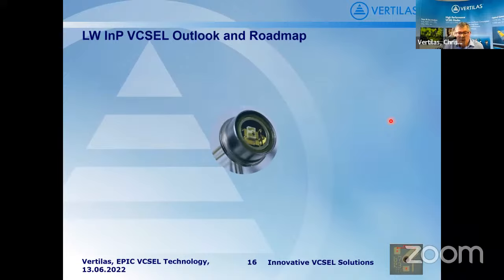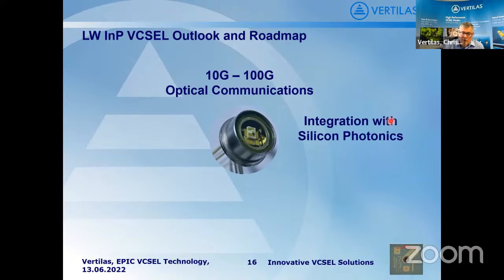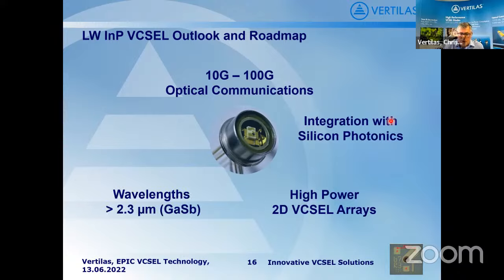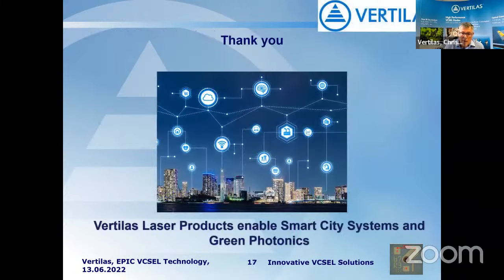Okay, so that brings me to my summary. This technology, indium phosphide VCSELs, allows you to address 10 to 100 gigabit optical communications. Of course, at module level, that's a multiple of that. Integration with silicon photonics. You can manufacture high-power 2D VCSEL arrays. With this technology, if you go to gallium antimonide, you can go even beyond 2.3 micron. And we also have a prototype technology for wide tunable VCSEL, which gives you about 50 to 100 nanometer tuning range. That brings me to my end. Thank you very much.